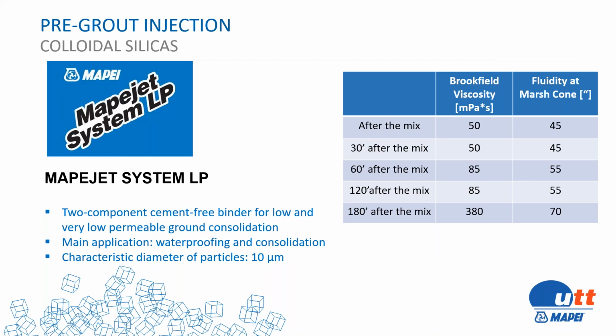We also have a product, the colloidal silicas, which you don't hear about very often. And MAPEI UTT has this great product that is a low viscosity chemical grout that can be injected to form an impermeable barrier into the ground. What we like about it is it's a good alternative to cementitious grouts, which sometimes cannot be pumped under pressure. This material is also a low pH grout, and it can penetrate, as you saw from the previous slide, into very, very small areas. It also makes it a little more commercially viable than using an acrylic grout.